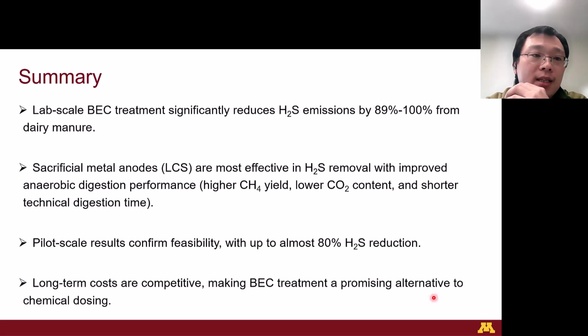To summarize, our lab-scale BEC treatment significantly reduced the hydrogen sulfide emissions by 89 to 100% from dairy manure. Sacrificial metal anodes, such as low-carbon steel, are most effective in hydrogen sulfide removal with improved anaerobic digestion performance. Our pilot-scale results confirm its feasibility with up to almost 80% hydrogen sulfide reduction, and the long-term costs are competitive, making the BEC treatment a promising alternative to chemical dosing.